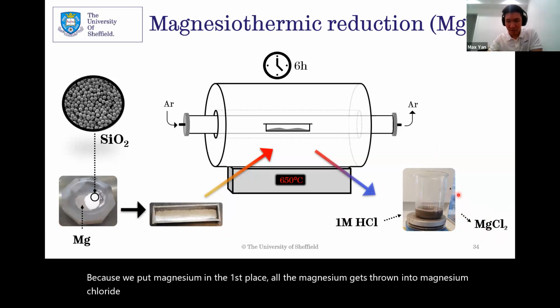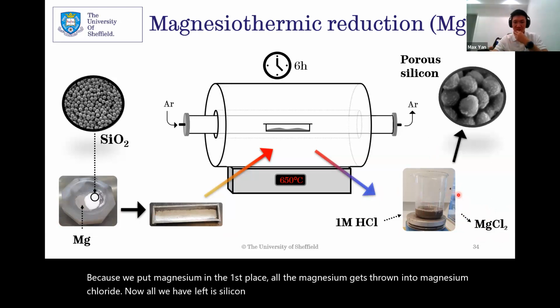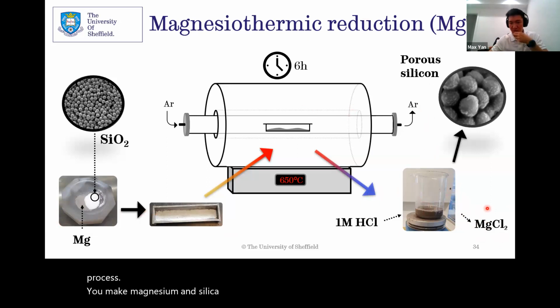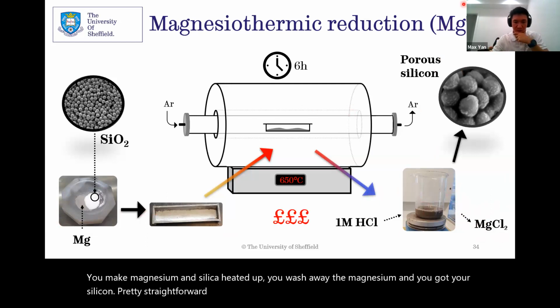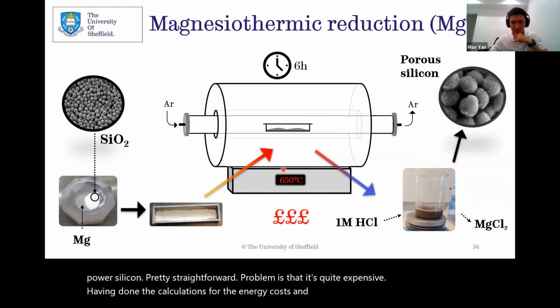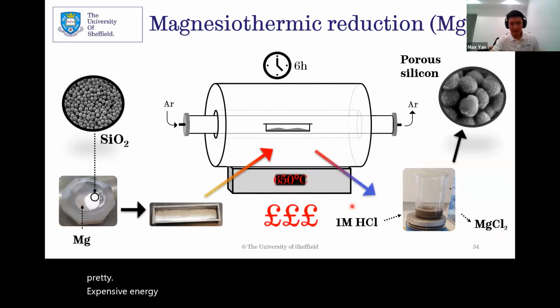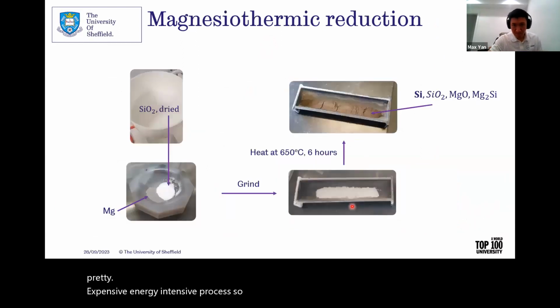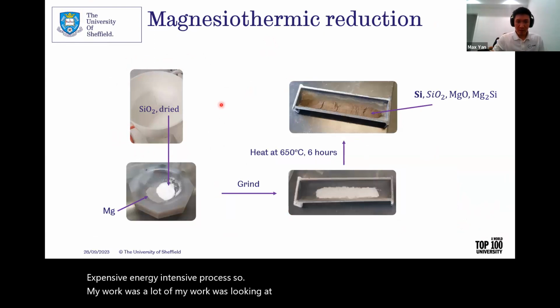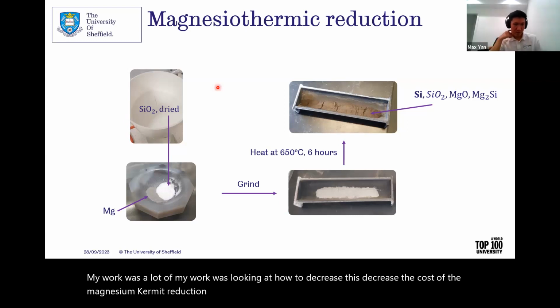Now all we have left is silicon, and this is porous silicon here. So it's a very simple process. You mix magnesium and silica, you heat it up, you wash away the magnesium, and you got your porous silicon. Pretty straightforward. Problem is that it's quite expensive. Having done the calculations for the energy cost and everything, 6 hours at 650 is a pretty expensive, energy intensive process. So a lot of my work was looking at how to decrease the cost of the magnesiothermic reduction process, which I'll talk about in a second.